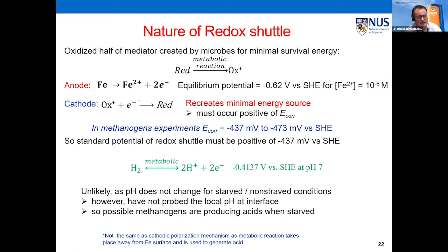However, when we measure pH changes between starved and non-starved, we don't see any change in the pH. So it doesn't seem that the bugs are making protons. However, we're not able to probe the local pH at the surface. If you try and stick a probe through your biofilm, you basically ruin it. So it's still very difficult to measure local pH changes at the surface. So it is possible that the methanogens were producing acids when starved.